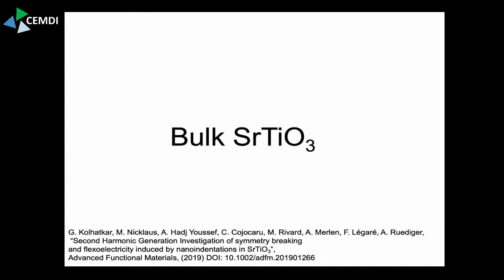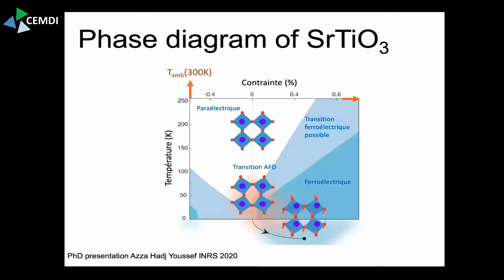And I promised you that would be a brute force approach. Why are we interested in strontium titanate? This is taken from the thesis of Azar. You know that if you change the temperature in strontium titanate, or if you change strain, then you can push the system from one crystallographic structure into another. You can get interesting properties like ferroelectricity induced in this material, which is a polar order. But you also get different kinds of transitions here. It's not only a polar order, but sometimes you have subunits rotating with respect to each other. So there's quite a bit that can go on in there.